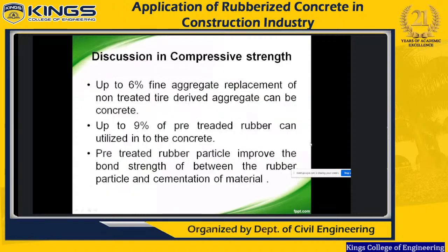So the compressive strength we obtained is maximum at 6% of non-treated rubber. They got 34.2. Thereafter it is a reducing scenario. This green color indicates the optimum replacement of 6% of non-treated rubber as well as 9% of treated rubber. So we observe that the maximum possibility is to add rubber without treatment at 6%.